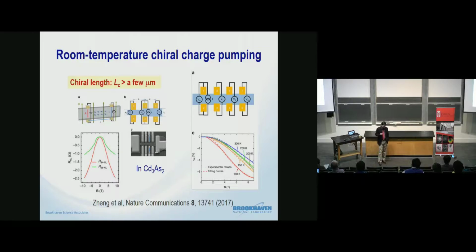The idea is that if you have regular scattering there, and if you put a contact here, apply an electric field and measure the voltage, measure the current here, that's what is usually localized, right? That's a localized effect over there because you're driving the electrons there. But what happened for the chiral particles? It turns out the chiral particle can diffuse for a much longer time. The reason is that they try to preserve their chiralities, okay? And it's protected, okay? And they found this distance can be a few microns, okay?